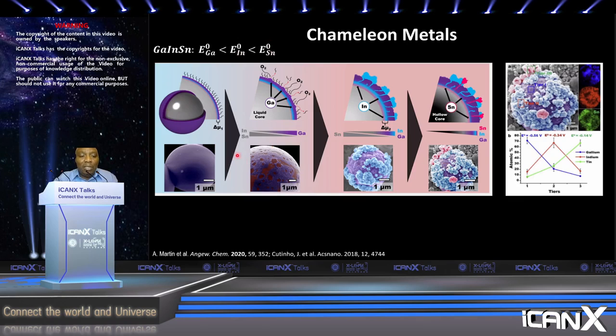The only interesting thing that we found is we see a lot of this fractal-like behavior growing on top of the gallium, and they are still rich in gallium. And we are exploring this further to revisit the theory of oxidation of metals, because this is a new interesting story by itself. But for now, we can see that actually we're getting composition inversion. We are releasing all the metals sequentially, and we can confirm that the components that are coming out at each tier are driven by the E0.